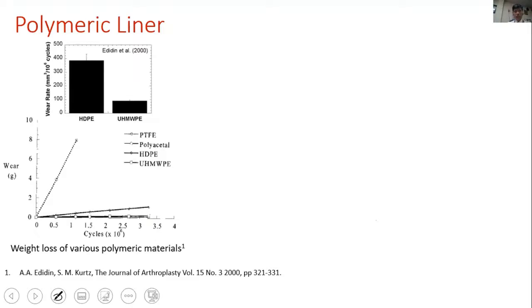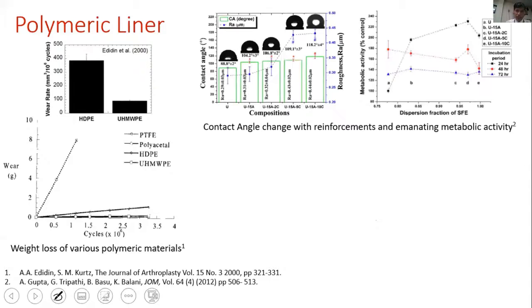If you see the literature, there is much literature available on what material we should use. There are various materials like polytetrafluoroethylene, polyacetal, high density polyethylene, and ultra high molecular weight polyethylene. But in all of them, it is shown that ultra high molecular weight polyethylene is one of the best because it shows the lowest wear rate. It is even 4 times less than high density polyethylene. So this is the lowest one we can ever get, and that becomes an automatic choice.